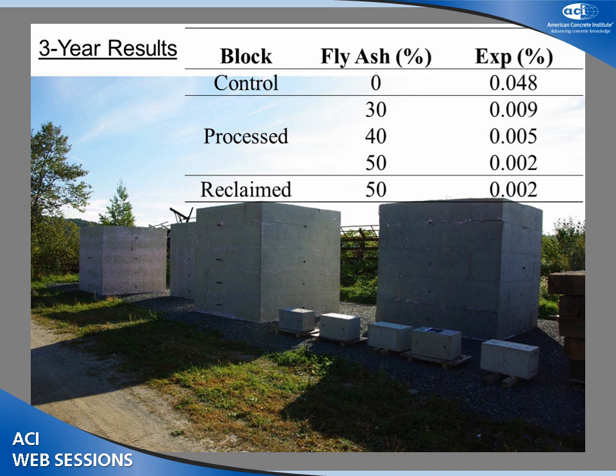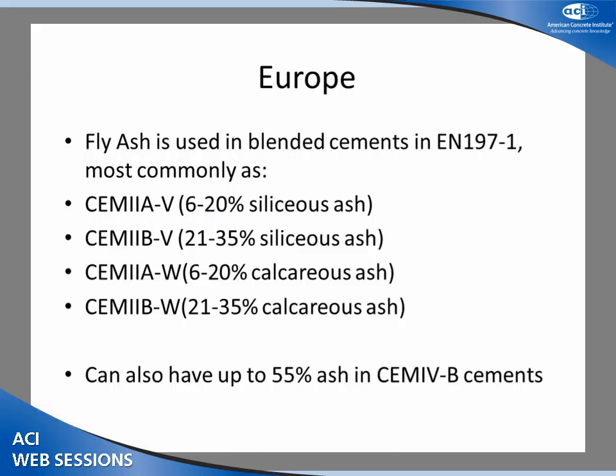It shows that they've already reached failure expansions on the control blocks without fly ash after 3 years in the field. But with the processed or reclaimed ash, they're not getting expansions. So they're looking at potentially using the reclaimed ash in those big blocks to rebuild the stand. Okay.